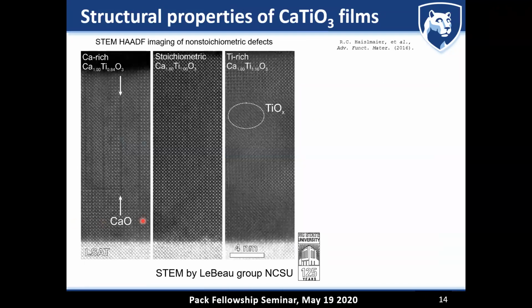And that this is really true, we later on figured out by taking cross-sectional scanning transmission electron microscopy images of the films grown, and we basically saw all of the typical defects that form in the film. On a calcium-rich condition, we typically form these stacking faults, these Ruddlesden-Popper faults. Because of the strain condition, the way we are growing this, they are all oriented out of the plane. For the stoichiometric condition, we get basically what we would expect to see for a perovskite film. And then as we go into titanium-rich conditions, you can see these moiré structures.